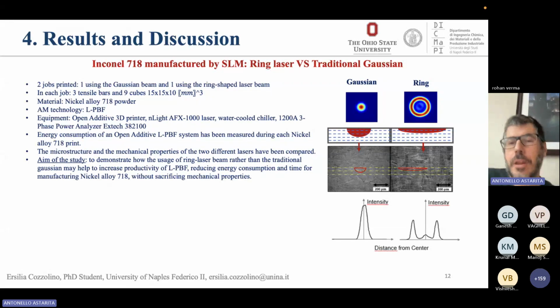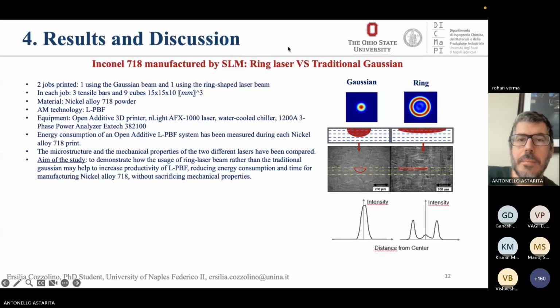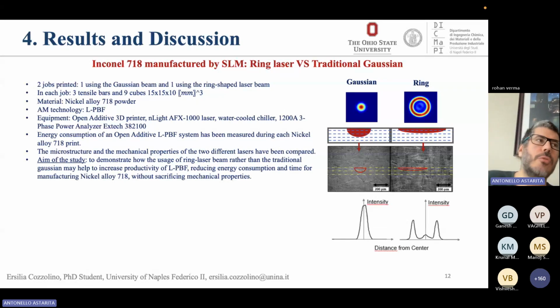And we did this experimentation on the same Inconel materials that I previously presented, but by using a selective laser melting machine, but by varying the profile of the laser beam from a Gaussian profile, which is the most used one, is the one that we use in the previous experimentation that I shown to you, moving to a ring laser. In ring laser, the shape of the laser is different, and we tried to understand if by varying this profile, we can reduce the energy consumption.